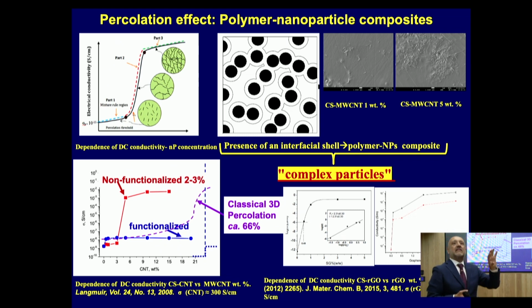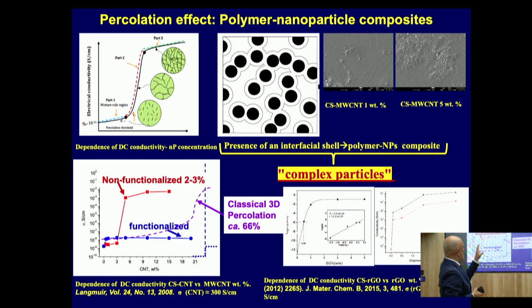That means that we have an interfacial shell with a pseudo composition between the matrix and the sphere. Of course, in this cartoon, we have hardcore objects. Materials, matter are not hardcore objects. We have ions, we have electrons jumping between different orbitals, or ions going through different materials, especially if you have the path to go through. So in that respect, that effective bigger shell allows an imaginary contact without actually having the contact.